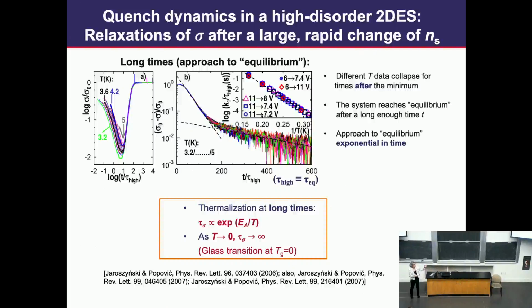However, if you calculate the numbers from here, we get at 1 Kelvin, for example, which is not a very low temperature, that this thermalization time is several orders of magnitude longer than the age of the universe. So for all practical purposes, the system is a glass.